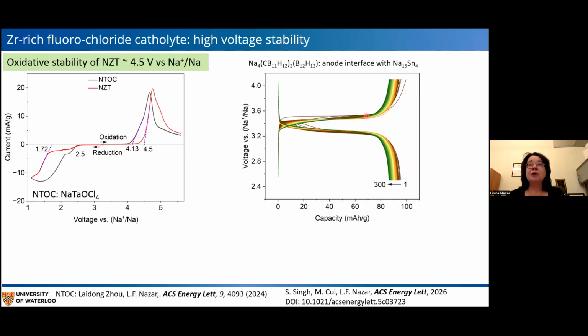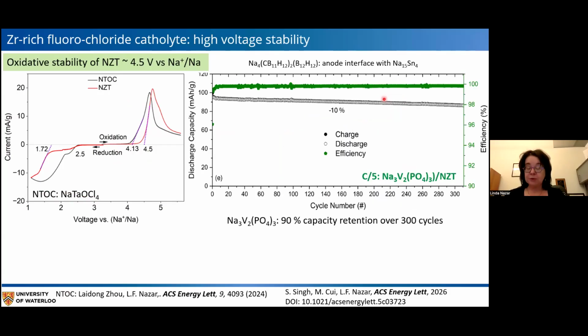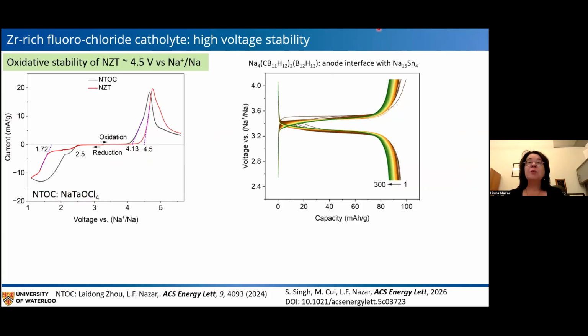And this just shows the charge discharge profile for this material with a sodium vanadium phosphate. And what we're using here that's off the screen: we are actually cycling these materials with sodium 15Sn4, the alloy, as our negative electrode, and we have to put on an interface of this hydroborate to basically stabilize the halide against the anode, against the alloy, because the chlorides reduce at a fairly moderate or high voltage, so that we have to protect this negative interface.